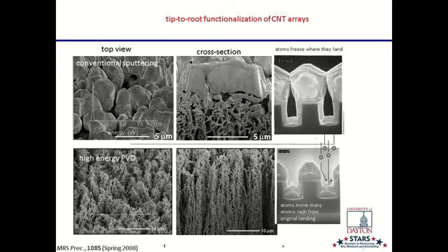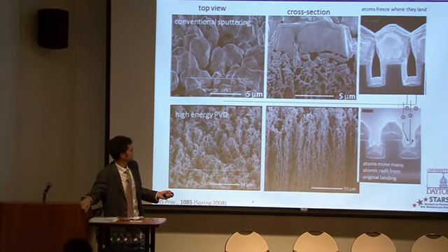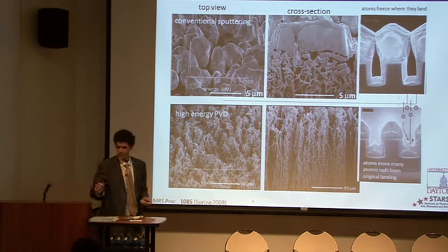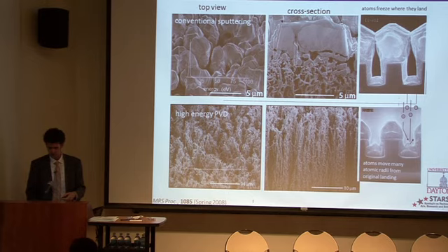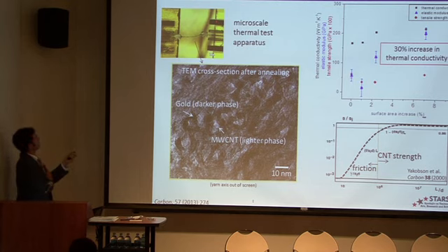We borrowed this idea from the microelectronics folks. If you use low energy particles, you get these kind of umbrellas on top. They grow together and keep any metal from penetrating deep inside these trenches. But if you use atoms that have enough energy, you can actually spread the metal out that's on the bottom and on the sidewalls and get it to redeposit from the bottom to the sides. And it'll also break up these features on the top. So by using this highly energetic ionized plasma process, we can penetrate deep into these forests and make these beautiful homogeneous gold nanotube yarns.